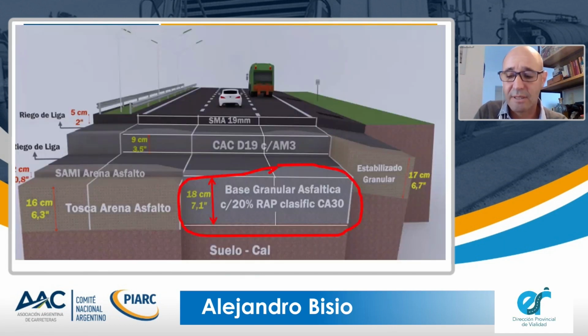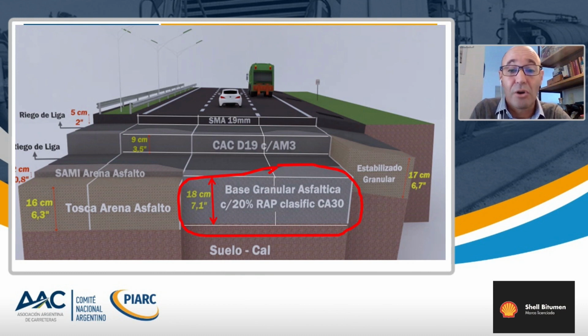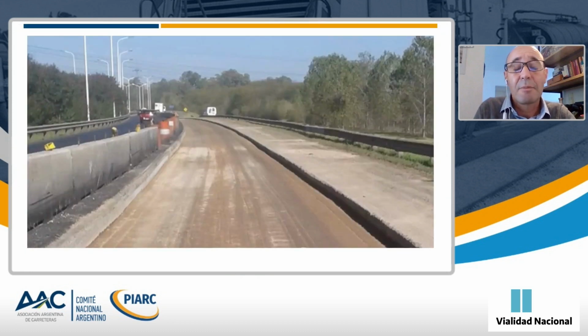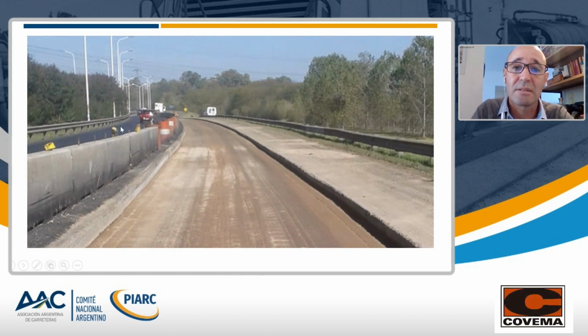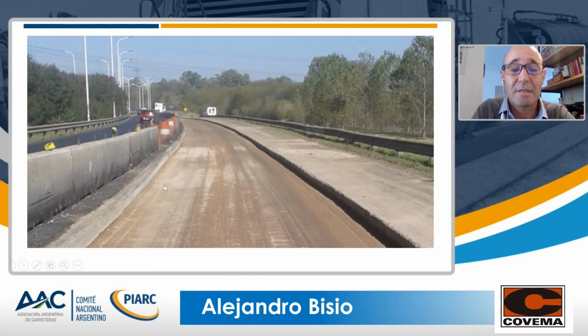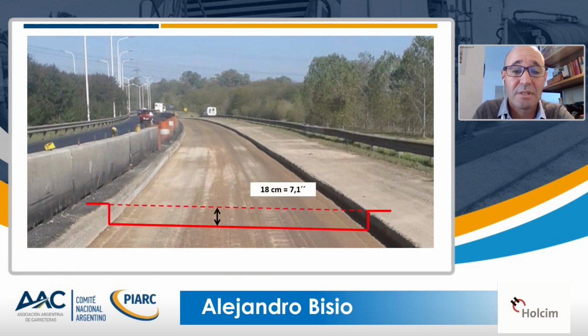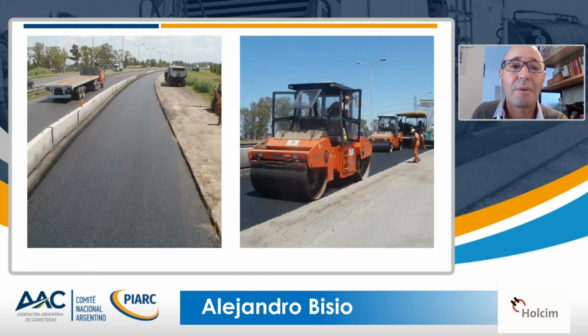As to the compacting, when this layer was laid as a subbase, 18 centimeters subbase, though this has nothing to do with recycling, sometimes we think that this type of mixture is more complex. I can tell you that you can see here a photo of the works. We had the fast speed lane, and then the two slower speed lanes. Once we had the mixture, we milled the overlay, then we had an 18 centimeters trench, and the mixed asphalt layer was laid in just one single laying movement, only one operation,